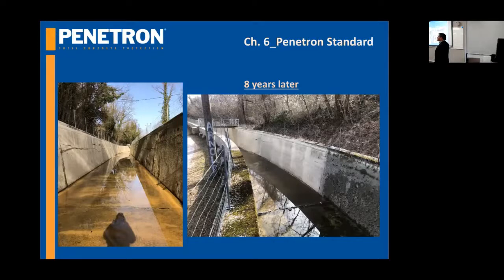An important thing concerning canals is that the Penetron standard used as a coating is very, very smooth. So if I'm the owner of a canal, I want to reach two conditions: that water wouldn't be lost along the way, and that water runs as fast as possible, because I have to produce electricity. With Penetron, we can achieve both, because the concrete becomes waterproof and the smoothness is granted. This is also important because there are no plants growing, which is typical. You can see moss and other organisms growing on the side of a canal.